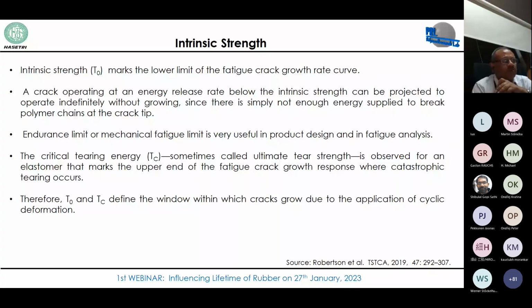The next part is the critical tearing energy, which is the other extreme of the fatigue crack growth curve, where it fails completely and catastrophic tearing occurs. In between, you have a stable crack growth zone, on which there are also a lot of recent publications. Therefore, T0 and TC define the window within which the crack grows due to the application of cyclic deformation.